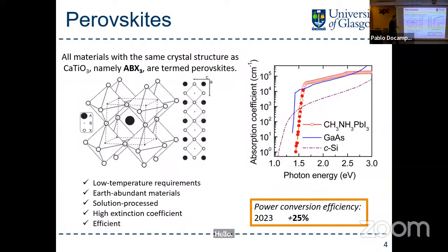Okay. So, perovskites. Why are we so interested in them? You might be familiar with the structure. It's got a spacer, you've got a lead center and some halide ions on the corners. And the interesting thing to me, and this is why I still show the slide after all this time, is that these are semiconductors you can print. So they're solution processable. And if you look at this plot over here, this is looking at the absorption as you get close to the band edge.